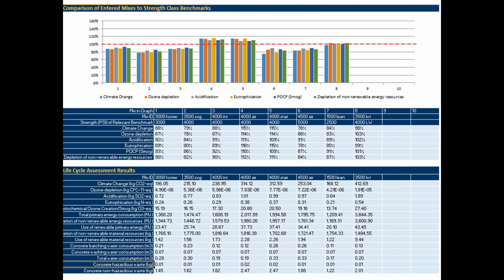And when they do that, they're not only looking at global climate change as one, they're making sure that at least 3 of these environmental impacts are lower than the industry average. So as we can see in here, that's the case. One thing to note on the mixes you're looking at: only one of these mixes actually used slag. If you look at mix 6, it actually had the highest cement content, which was 600 pounds total cementitious with 25% slag. Mix 1, 2, 3, and 7 were all using fly ash. So we can see that as we use slag, we lower our numbers.